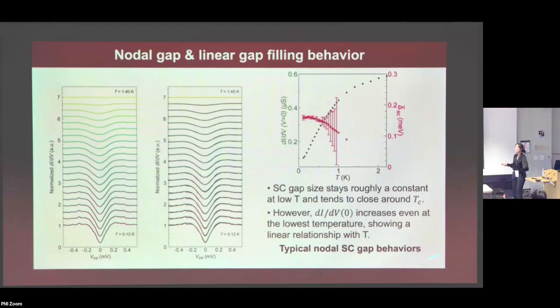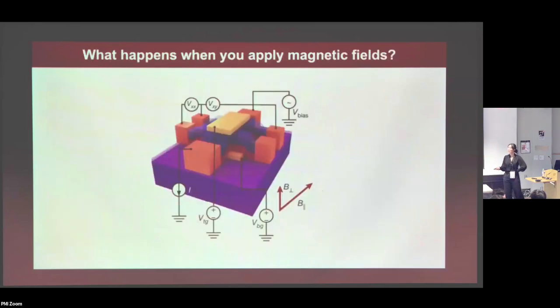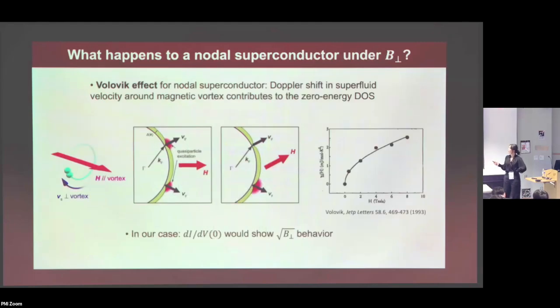Okay, so this is very typical nodal superconducting gap behavior. But still, some of you might say, this is temperature, you might just be exciting some other things. So then we can do further measurements. Now we can do some complementary measurements using magnetic fields to perturb the density of states of the superconductivity. We can first look at what happens if you apply an out-of-plane magnetic field. Typically in nodal superconductors, there's this thing called the Volovik effect. If you apply an out-of-plane magnetic field, you basically have a Doppler shift in the superfluid velocity around the vortices that contributes to a finite zero energy density of states.